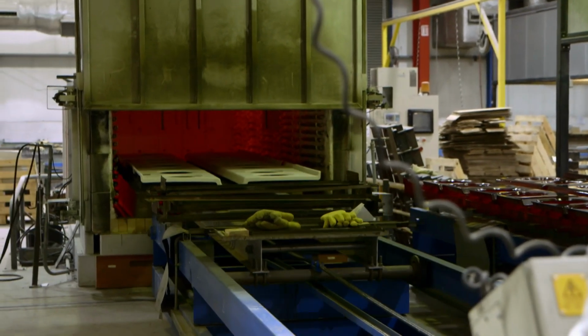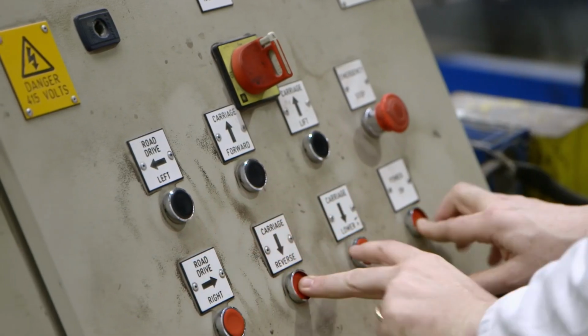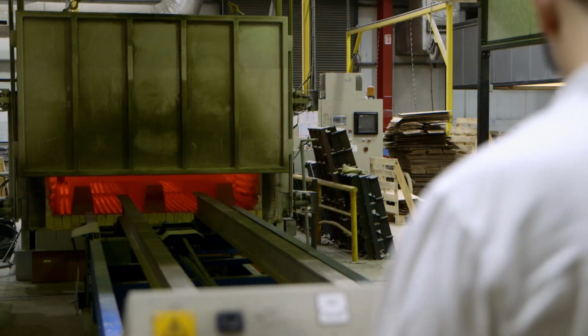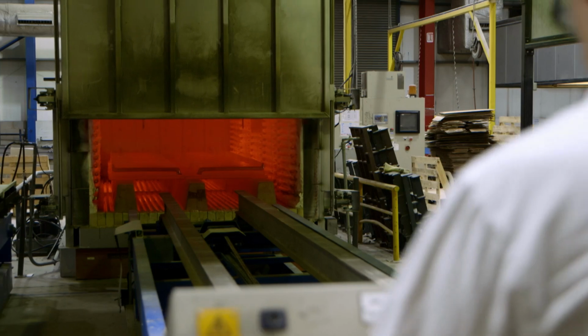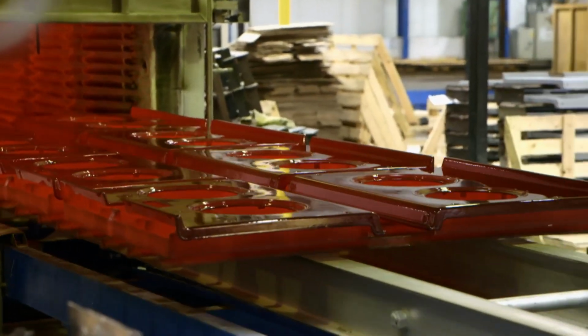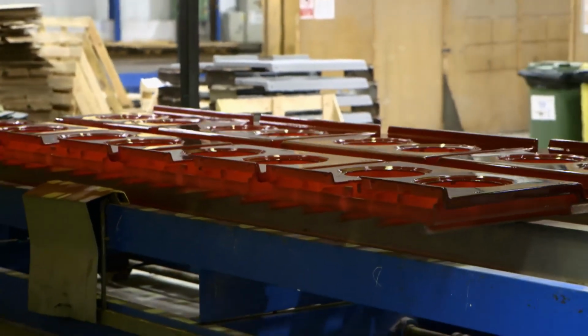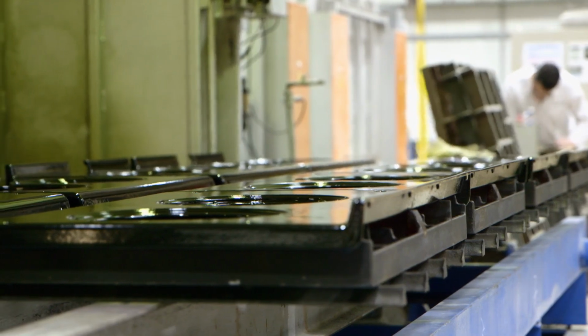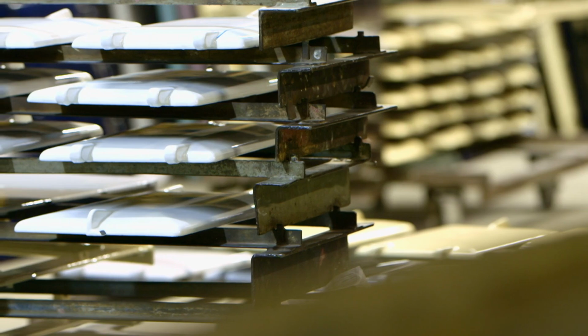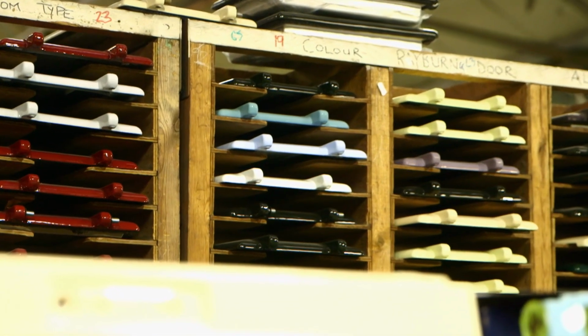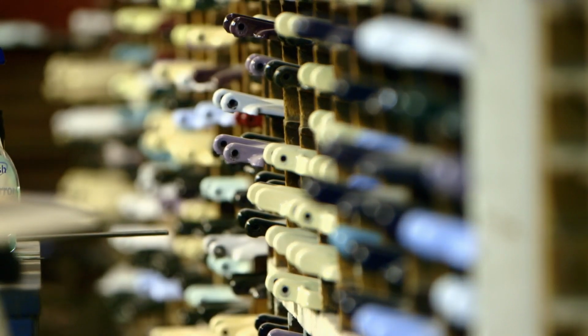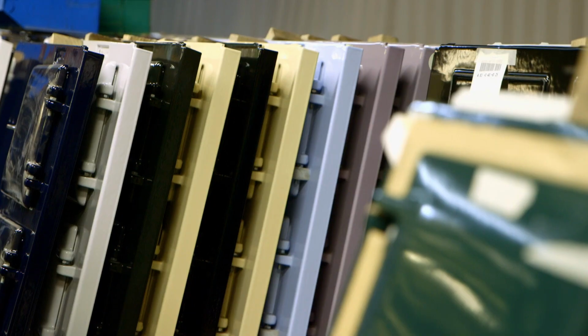Enamel is made up of tiny particles of glass and is sprayed onto the cast iron. It is then baked in a furnace at 800 degrees Celsius until it is literally red hot. This fuses the enamel onto the cast iron. This process is repeated 3 times to produce a smooth, high-gloss finish, which is very easy to keep clean. The parts, door and tops are all colour matched for each individual model.